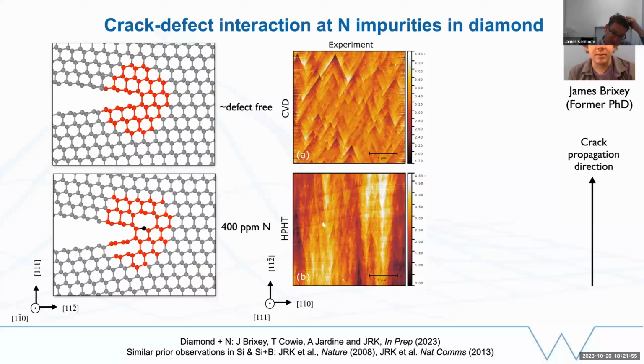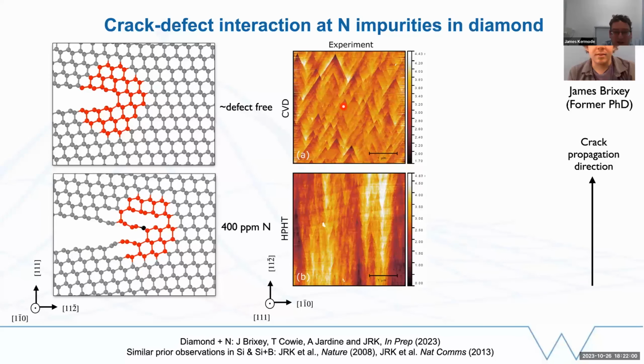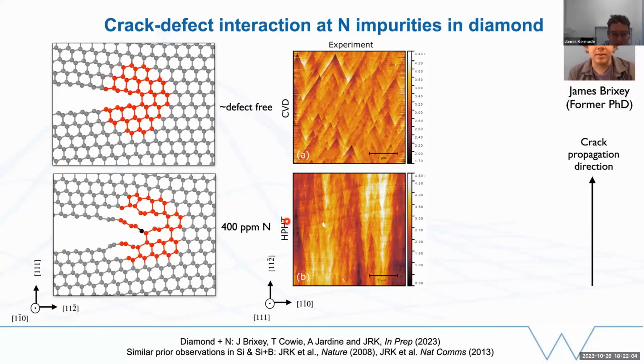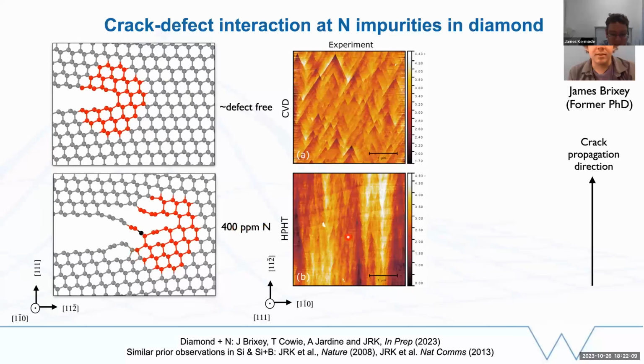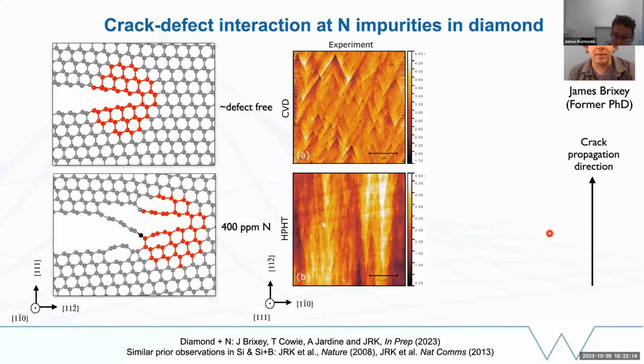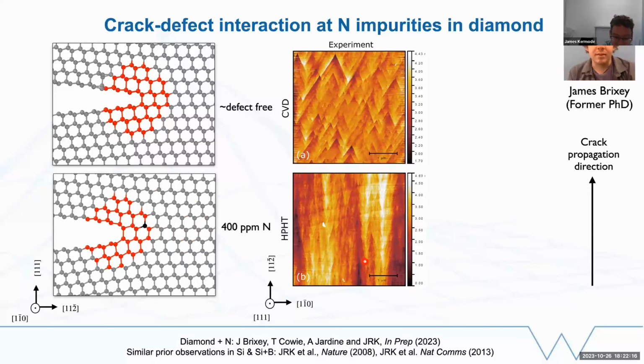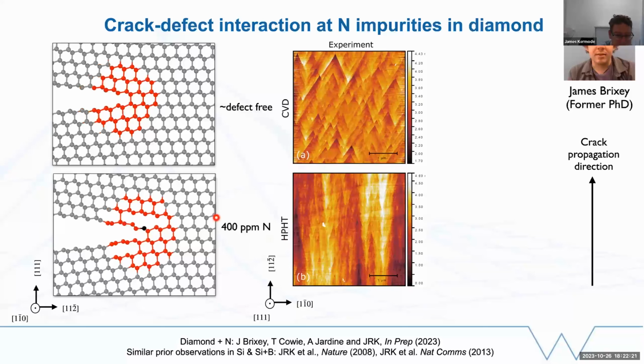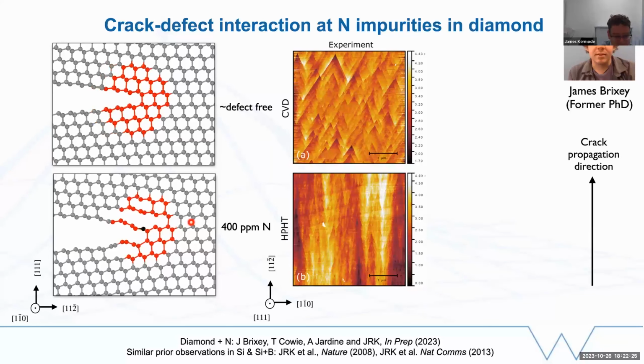So if we look at some experiments, in the upper case where there are hardly any defects, we see a few features on the fracture surface, but not too many. Whereas if we look at a specimen which contains significantly more nitrogen, 400 parts per million, we see a real forest of these ridges on the fracture surface. So here, this is the crack propagation direction, cracks are moving forward. And the hypothesis is that these little triangular features correspond to individual steps where cracks are interacting with defects and stepping up out of the fracture plane.